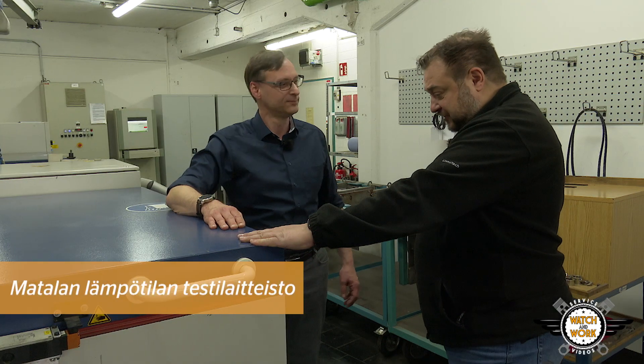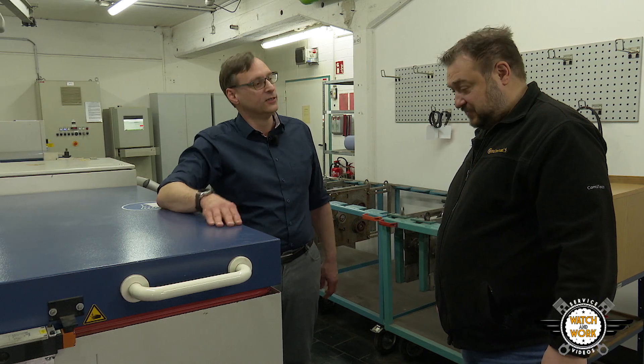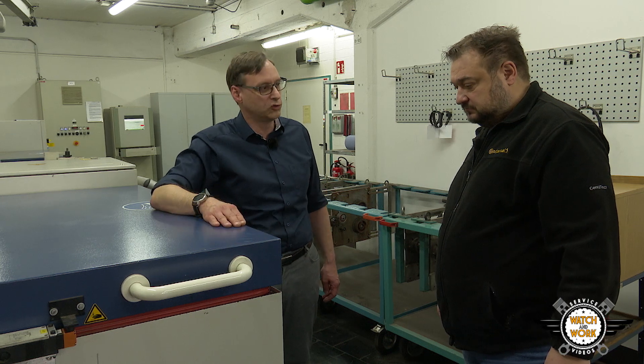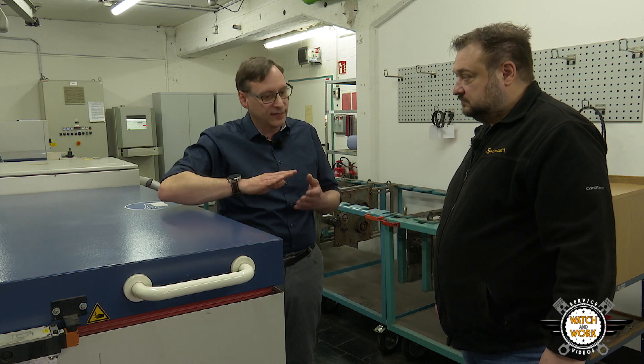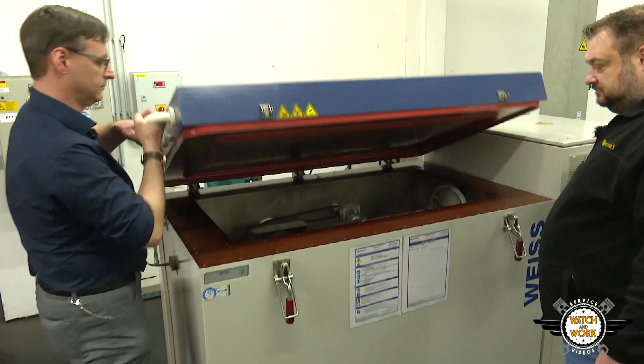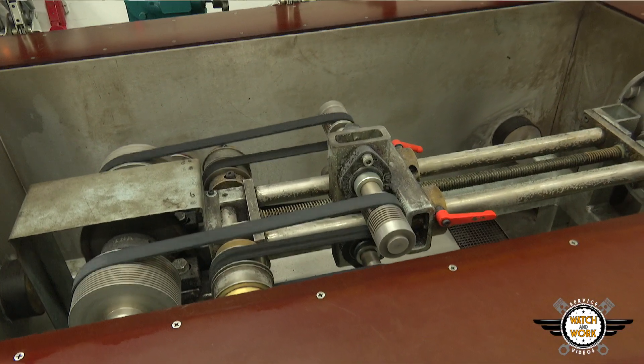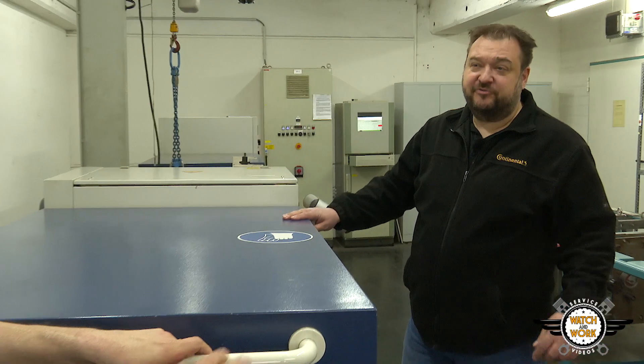It looks as if things are about to get chilly. You're absolutely right. These are our low temperature test rigs where the belts are tested for resistance to the cold at minus 40 degrees. That's really cold. Imagine you're in a ski resort and leave your car outside overnight — when you start the engine in the morning, the belt will be frozen when it starts running around the pulley. It must still be elastic and not kink so that the compound doesn't start to crack. So the belts are started here more than 100 times at minus 40 degrees to check they run smoothly. I wish I could go on that many skiing holidays.